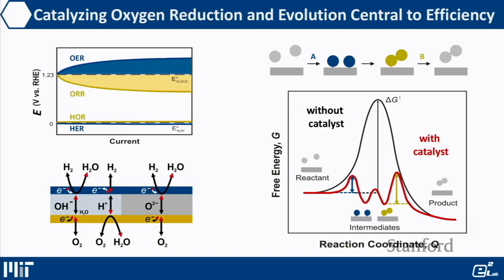So we first need to, because oxygen redox is universal for the production and use of all these energy carriers, figure out ways to improve the kinetics of these processes. Regardless of whether you operate oxygen redox in acid or alkaline solution, or at elevated temperature at the oxide-oxide interface, these kinetic limitations exist. One can design catalysts to reduce the barriers between the reactant and product.